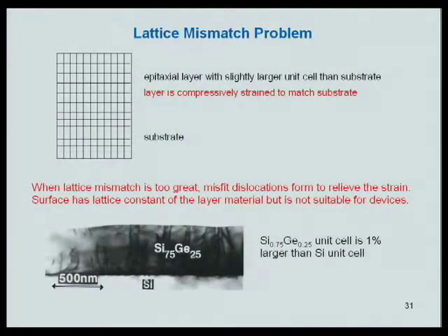And these strained layers are good for many applications because strain modifies some of their properties in a desired way. But if the mismatch is too large, in this case, the difference in the unit cell size between 25% alloy of silicon germanium and silicon is only 1%, but this is too large to grow a good quality epitaxial layer.